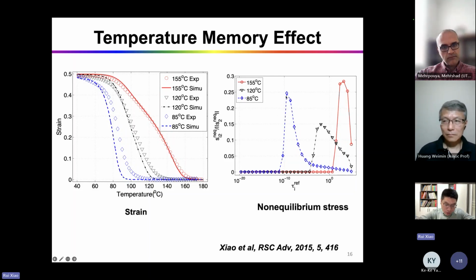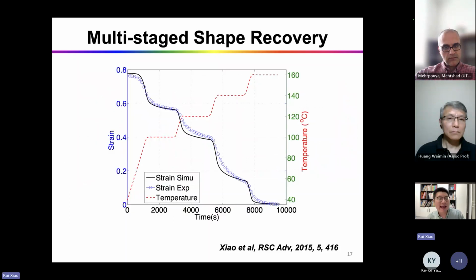So basically, you have broad glass transitions, and when programmed at different temperatures, different processes fix the temporary shape. So that explains the temperature memory effect. It can also reproduce the multi-stage shape recovery—you can see that you can recover at different temperatures, and the whole recovery process can be split into different parts.